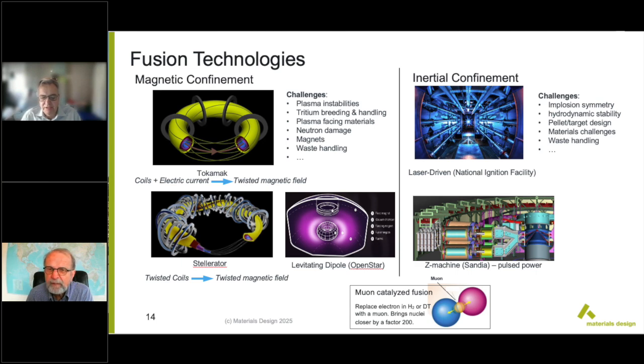The other aspect, nuclear waste, probably refers to the fact that absolutely when you have materials under neutron bombardment, take carbon, if you bombard a carbon with a neutron and the neutron actually hits the nucleus and combines with it, then you end up with carbon-13, which itself is stable, so not much of a problem. But if you hit it again with another neutron, you end up with carbon-14, which is radioactive. So the upshot of that is that even in nuclear fusion, radioactive waste does get created. It's usually relatively low-level radioactive waste.